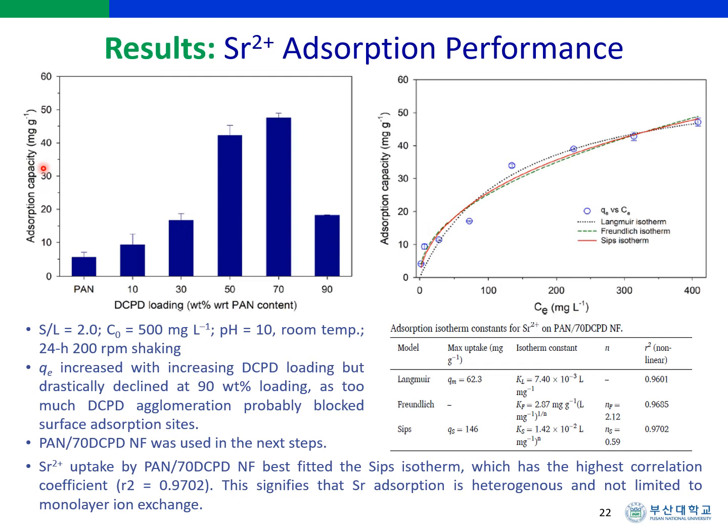The composite adsorbent demonstrated relatively higher strontium uptake capacity owing to two major qualities of the DCPD particles. One, the lamellar structure of DCPD provides more free interspaces. And two, almost all the calcium sites in the DCPD lattice are occupiable by strontium atoms. Furthermore, a balance between DCPD loading and aggregation occurred at 70 wt% DCPD loading.